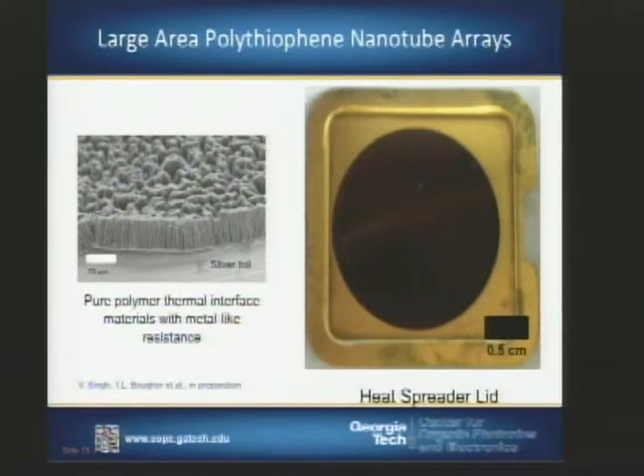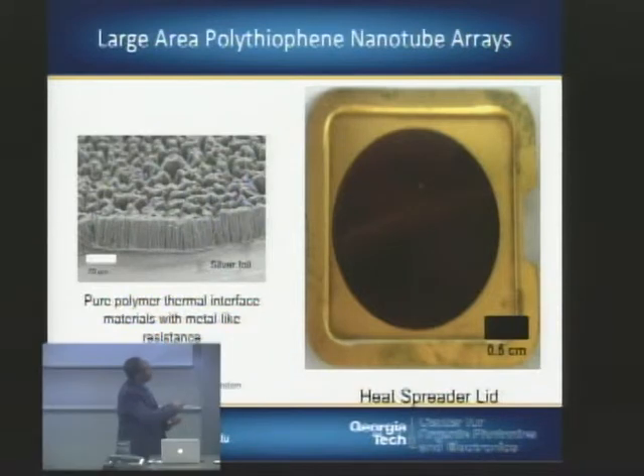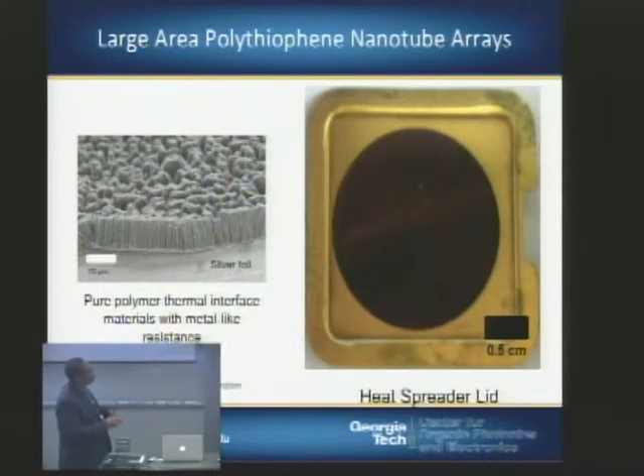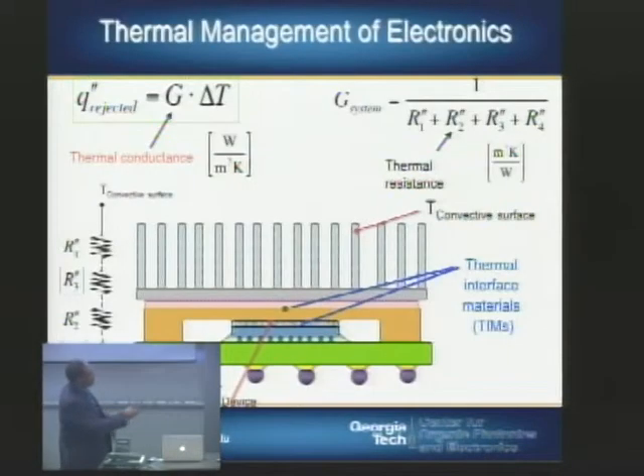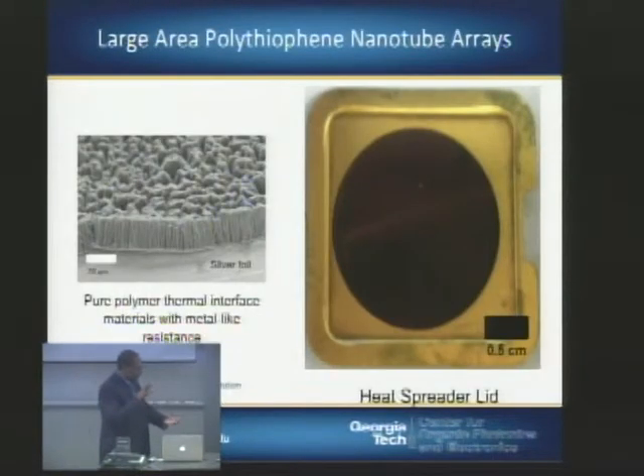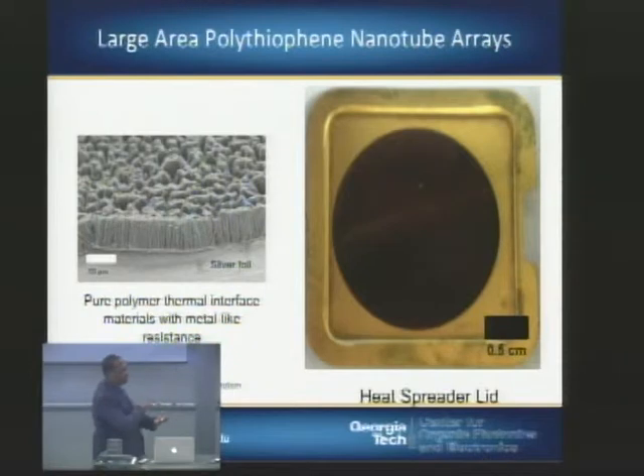Professor Cola has come up with a very unique way of developing polythiophene nanotube arrays. Typically you think of polymers as having low thermal conductivities, but through the creation of these polymer nanotube arrays, he's able to get, very similarly to what Seth showed earlier with the carbon nanotubes, very, very large contact areas. He can actually grow them and place them on these metal lids, which you may consider as the metal lid that goes over the top of the device. And so it provides a nice conformal and soft contact to this particular device.